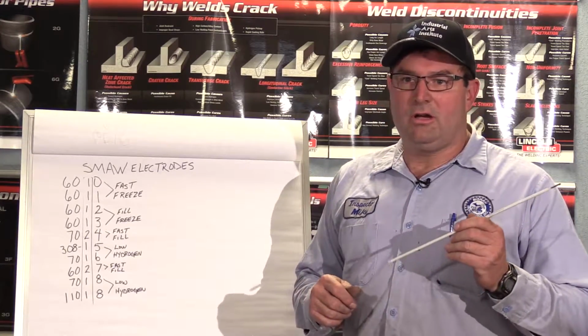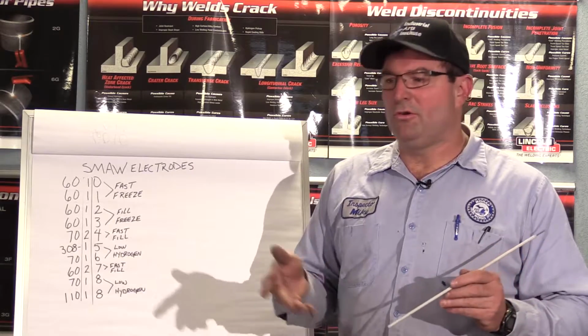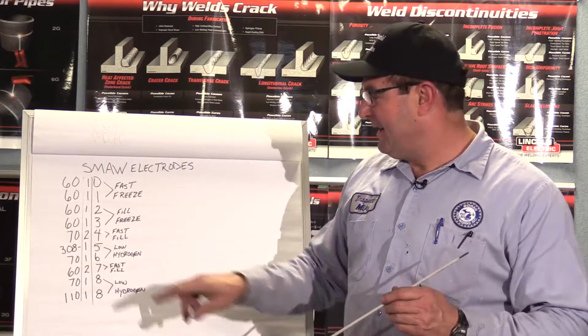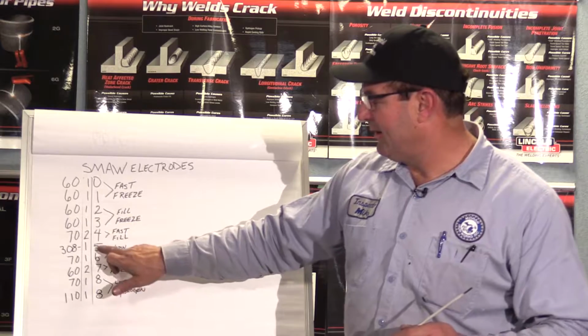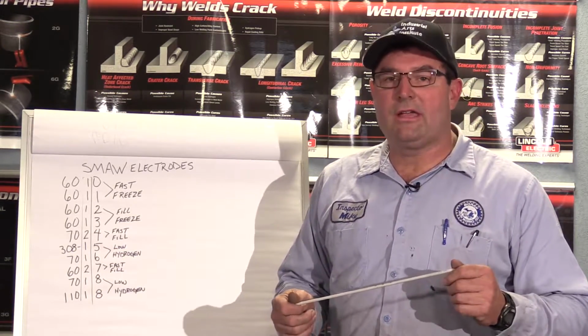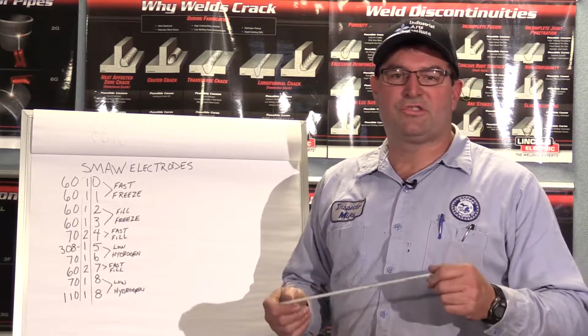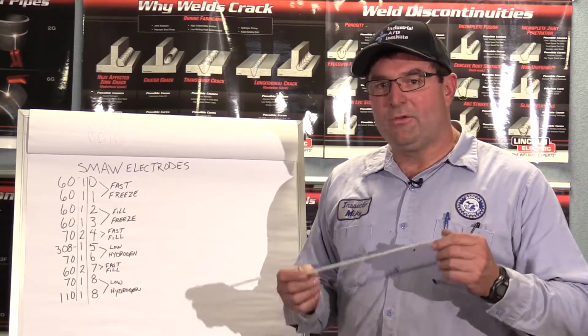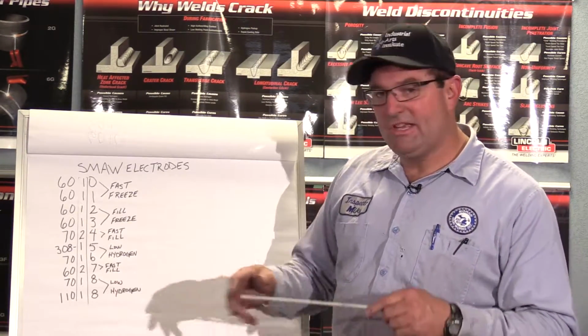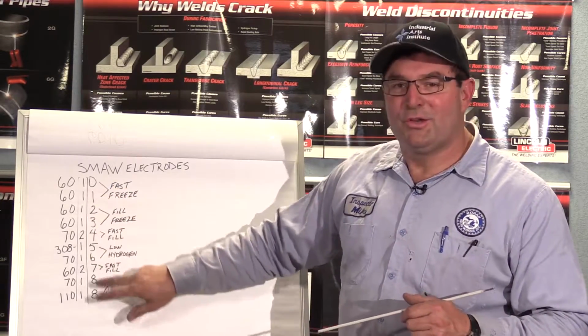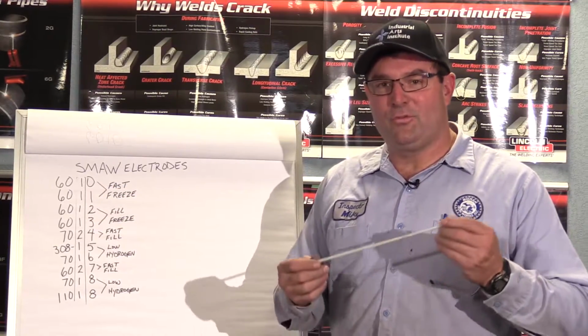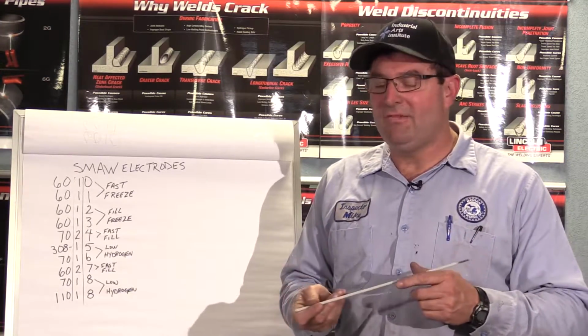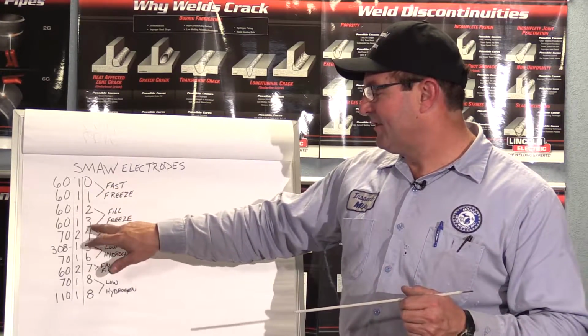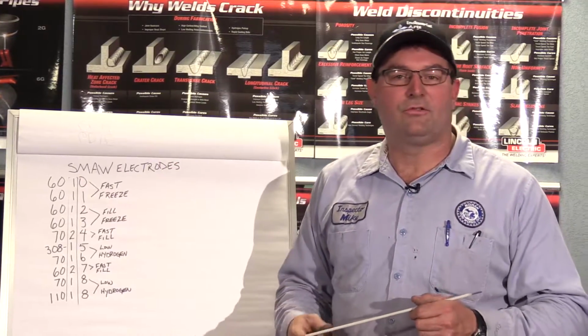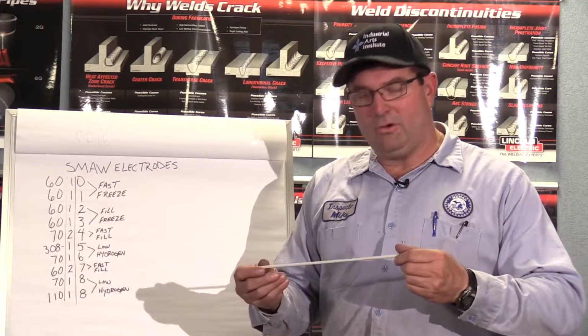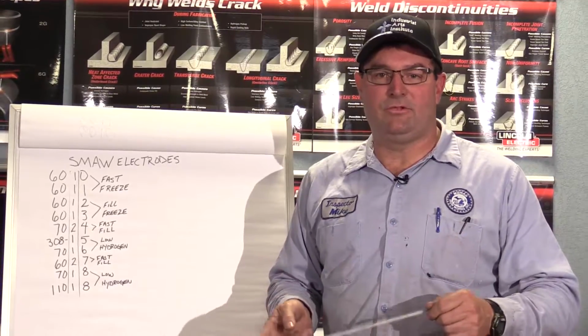Where I work now, the majority of stuff we weld is most anywhere. You go to a power plant or shipyard, I cannot use any of these electrodes other than low hydrogen. They're that concerned about cracking. 7018 being the most common electrode anymore. The other thing, if I qualify with 7018, it covers all these other electrodes. So in the last video when we showed qualifying, why were we using 7018? It would cover me for 6010, 6013, and all the other electrodes. So that's why it's the thoroughbred of welding anymore, 7018 in the SMAW world.